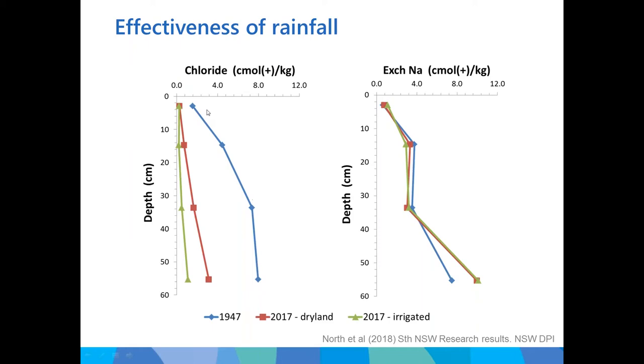Over that 60-year period, with just rainfall, we've had a significant amount of leaching since the 1940s. And with irrigation, we've even lost a little bit more chloride. The difficulty is that, as you see on the graph on the right, we haven't really shifted sodium. These are freshwater or rainfall sites, so they won't have had gypsum programs. If you were going to add gypsum to these sites, then I would expect that some of that sodium would have shifted. But the point behind this is that rainfall can be quite effective in shifting salts. You do need to keep adding the gypsum in order to shift the sodium.